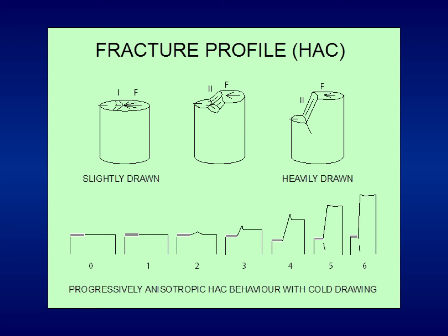behavior. In the bottom of the slide, we can see these profiles with increasing deflection angle with the increasing degree of cold drawing. This means a progressively anisotropic hydrogen-assisted cracking behavior with cold drawing, with increasing hydrogen-assisted cracking path deflection angle with the degree of cold drawing.